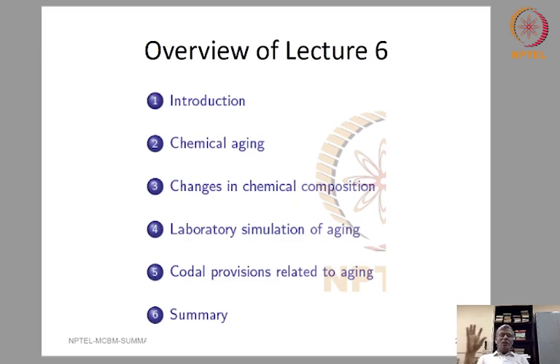Now the aging that you are interested in is more or less, in my opinion, the aging that happens due to oxidation. Okay, you can have reversible aging, you can have irreversible aging. Reversible aging that happens at room temperature is called steric hardening, and reversible aging that happens at low temperature is called low temperature physical hardening. From the perspective of measurement, it is necessary that the engineer ensures that the material he is testing has reached a steady state, because if you don't condition the material properly, your data is going to be spoiled due to steric hardening or low temperature physical hardening, right?